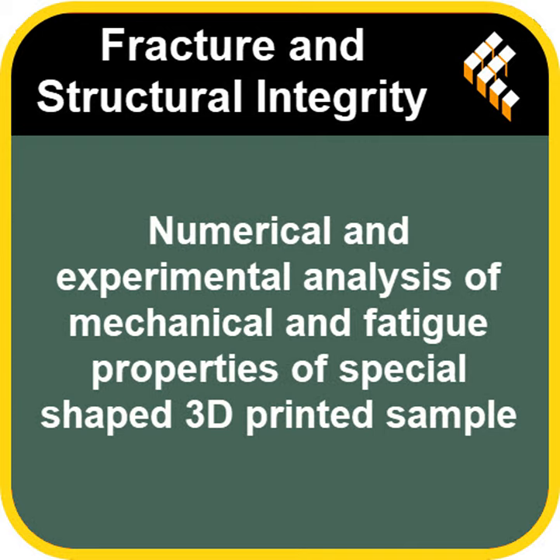Okay, critical equivalent plastic strain. That sounds like some serious engineering jargon. Can you break that down a bit? What is that in practical terms? Think of it as the point within the material where it has deformed permanently. It's gone past its yield strength, and it has essentially run out of capacity to absorb any more stretching or deformation without actually fracturing. The simulation pinpointed exactly where that breaking point, if you like, would form first under the increasing load, and the physical test confirmed that prediction perfectly. Wow. So this means the inverse analysis calibration method is robust. It's robust enough to predict these complex failure modes, even in optimized, structurally challenging geometries designed to induce shear.